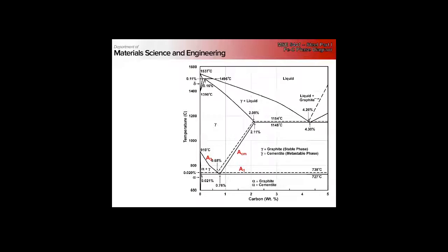You need some undercooling or overheat to get things to happen, right? At the equilibrium temperature, you don't have any driving force. So the dashed line represents the solvus on heating, and the solid line represents on cooling, and the distance between the two is the hysteresis,